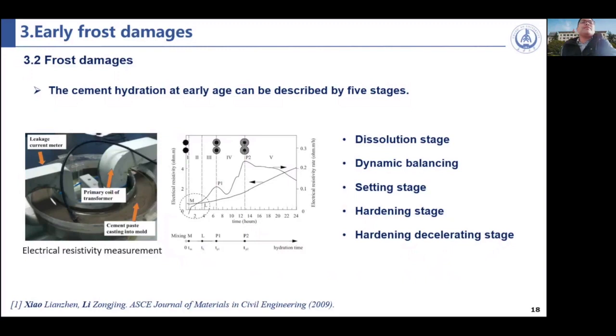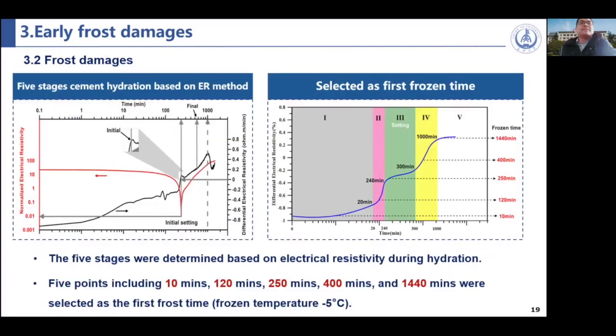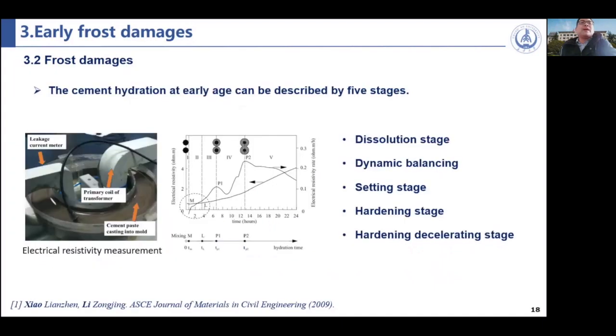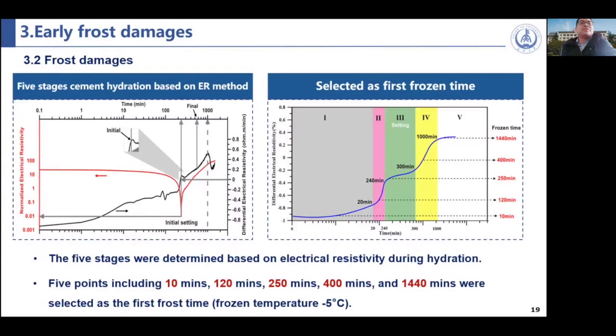So firstly, we measured our cement paste with this machine, and we got the 5 stages, especially the 5 stage points based on the electrical resistivity during the hydration. And then we got 5 first frozen times located in these 5 stages. You can see from this picture.